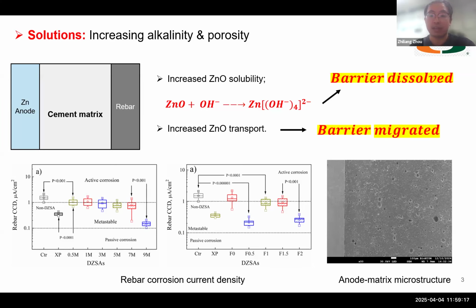And our past studies have shown the high effectiveness of these two methods in anode modifications. Our experimental data shown here indicates the anode's performance can be significantly enhanced with a high pH value close to pH 15. It's very, very high pH value. And the anode's performance can also be enhanced by the higher porosity, even by more than 20%.